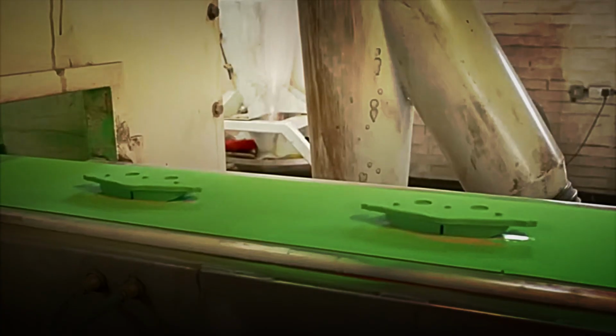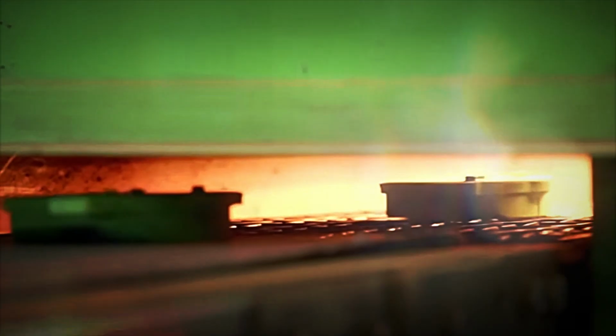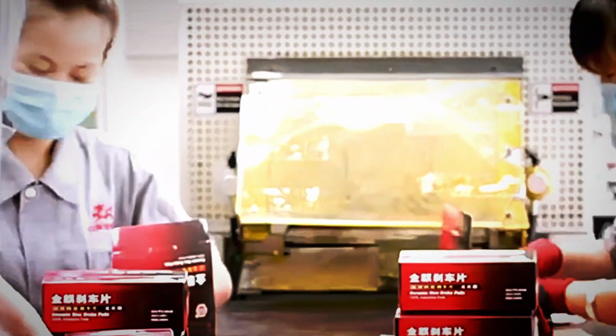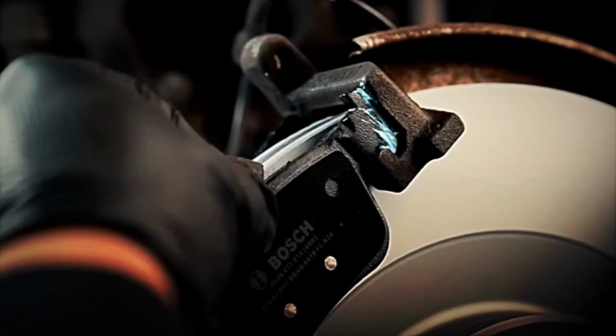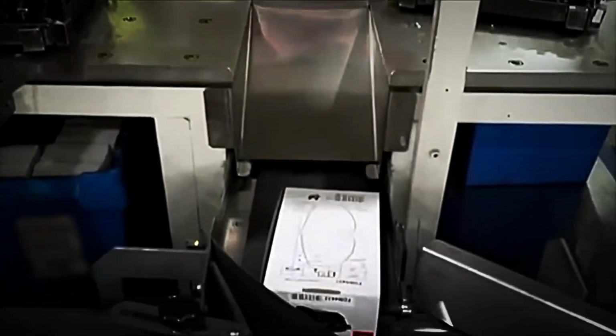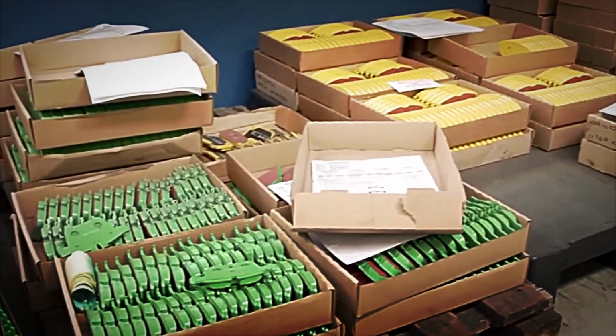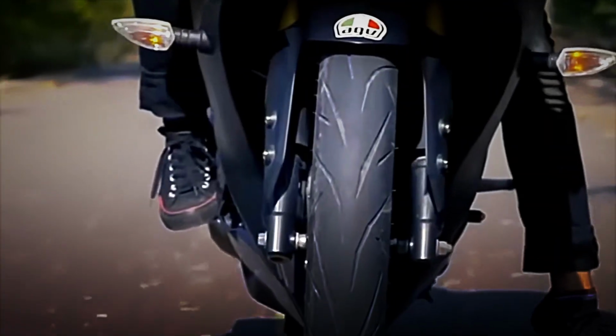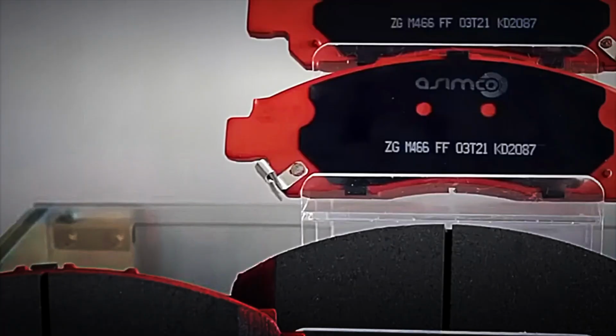Once the pad reaches its final geometry, the application of a surface coating begins, whose function is to optimize its initial performance and protect the friction surface. This treatment consists of an extremely thin layer of specific compounds, among which molybdenum disulfide stands out, selected for its ability to reduce friction in the early stages of use. The application is carried out in a controlled manner to ensure uniform coverage, without altering the dimensions or the tolerances obtained during machining. This coating plays a key role during the first braking cycles, as it facilitates a gradual settling between the pad and the disc.